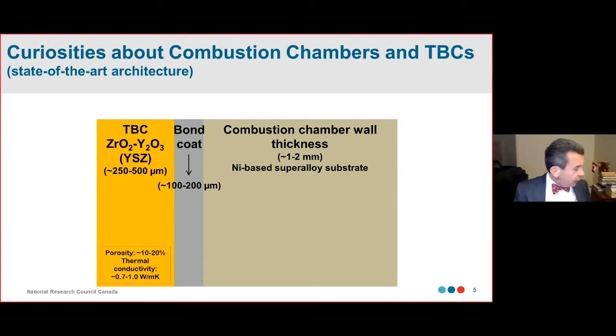The standard material we use today for the ceramic TBC is zirconia yttria, and the acronym is YSZ. So in my presentation, I'm going to say the acronym YSZ many times. It's the zirconia yttria, the material of the TBC. The thickness varies from 250 to 500 microns, the porosity of that ceramic TBC varies from 10 to 20%, and the thermal conductivity from 0.7 to 1 watt per meter Kelvin.